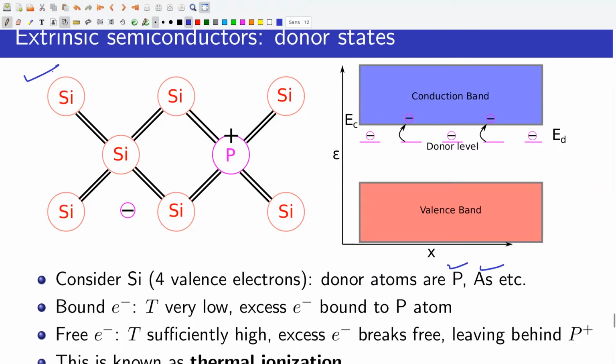The impurity atom substitutes a silicon atom in the lattice. It has been confirmed by lattice constant studies that the pentavalent impurities enter the lattice site by substituting a silicon atom, and such impurities do not enter interstitial positions. A pentavalent phosphorus atom forms 4 covalent bonds with 4 nearest silicon neighbors, and 1 extra valence electron of the pentavalent impurity is left over.